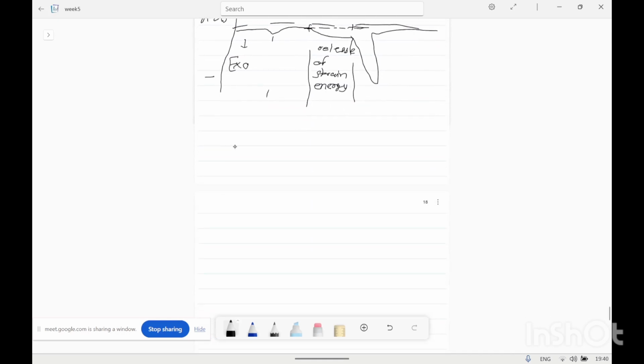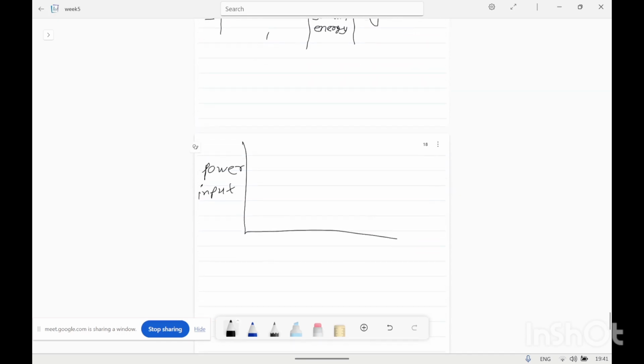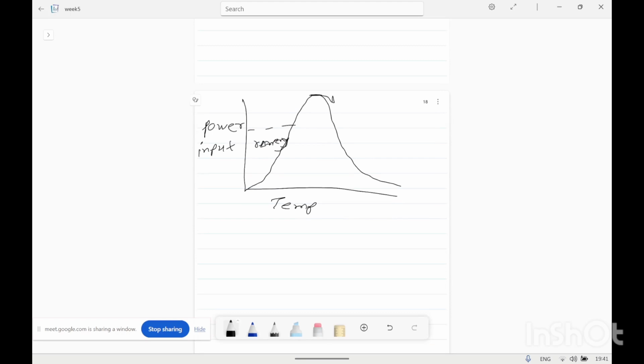So during the recrystallization process, if we plot a diagram between power input and temperature increase, the power input increases and then decreases. So this process is called the recovery process, means power input is increasing. At the point where recrystallization starts, the decrease in power input happens because of the release of strain energy that helps in the recrystallization process. In this portion, the power input is decreased.